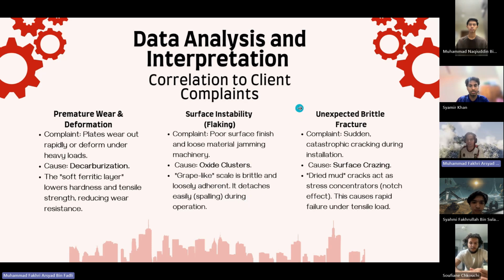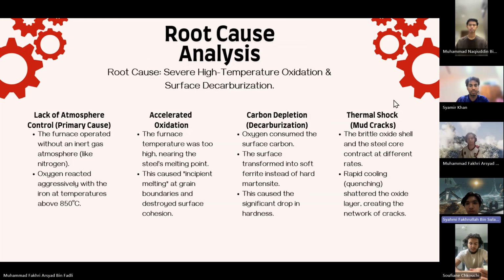And the third one is unexpected brittle fracture, which is sudden and catastrophic cracking during installation. It is caused by the surface crazing, which can be seen by the dry mud cracks as the stress concentration. This causes rapid failure under tensile load. This one can be seen under the 100 times magnification from the material given just now. So, move on to the root cause analysis.